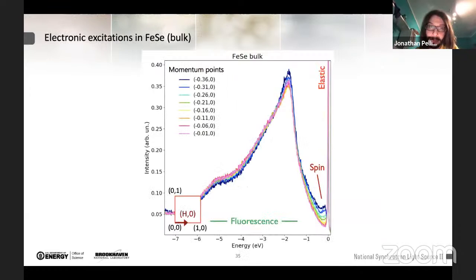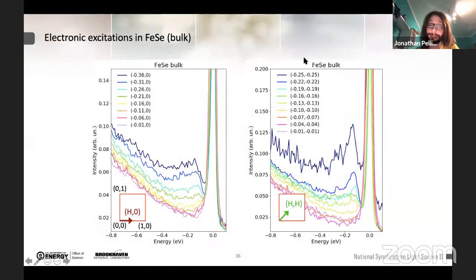Then the next step that we did was to measure the RIXS on iron selenide bulk. And this is how a typical RIXS spectrum looks like for bulk material. So we have in the high energy loss region between 1 and 6 eV a strong fluorescence background. And in the low energy region, we have the elastic line at 0 energy loss. And we can see here peaks of the spin excitations at different momentum. If we zoom in to see these peaks better, we can see that these spin excitation peaks that I'm showing here disperse as a function of momentum.